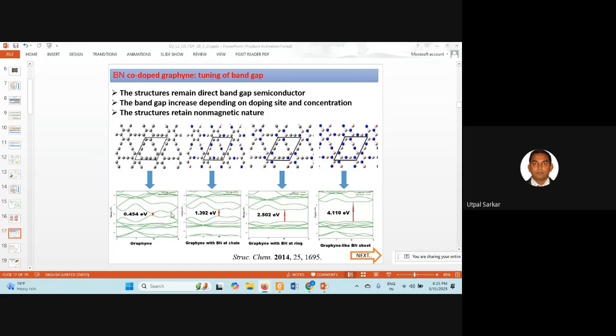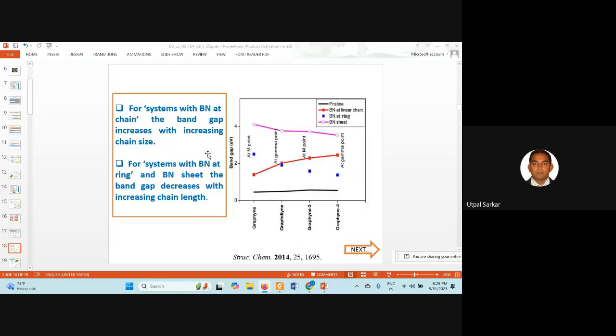So the band structure, in all these cases, you see, is a direct band gap semiconductor, and the band gap increases depending upon where you are making the doping, so the doping site, and also on the concentration, and all these structures are basically non-magnetic. We have done some spin resolved calculations, and that shows there is no spin asymmetry in the band structure.